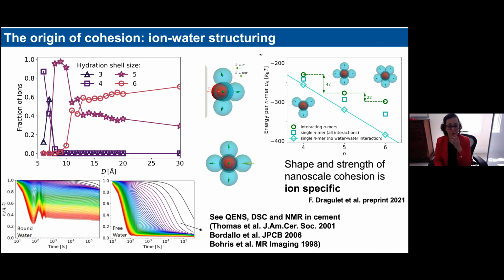Also, the other very important consequence is that, because the role of the water and the dynamics of the water change as we go in this direction, increasing the confinement of ion and water in between the two surfaces, as I was explaining, you start to see basically two populations of water. One population of water is characterized by relatively fast dynamics, which in fact has been detected in experiments using scattering and, for example, NMR.